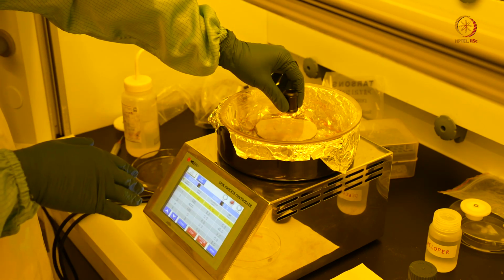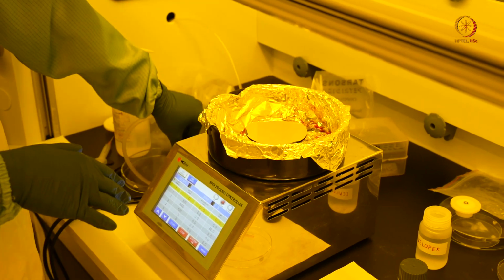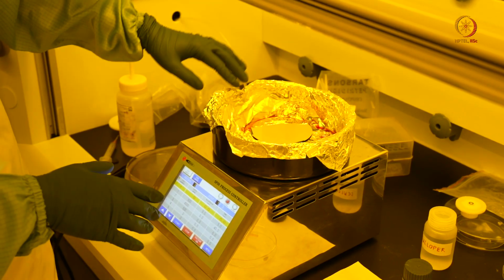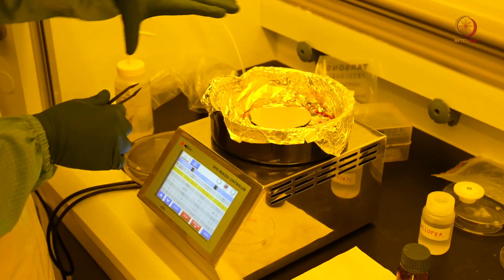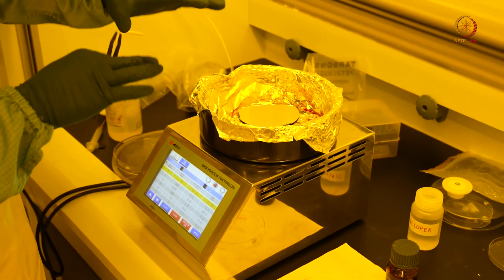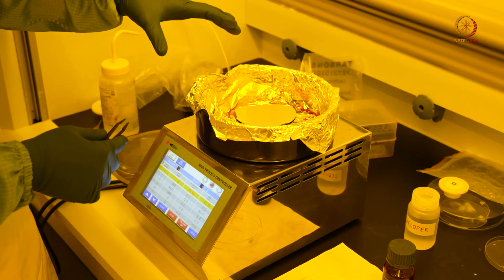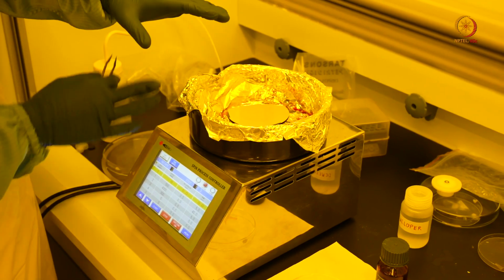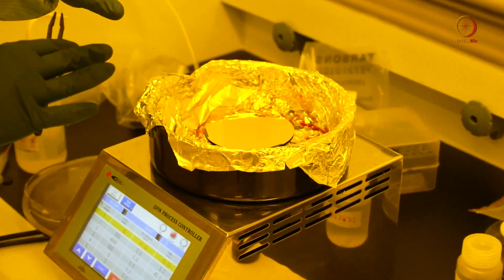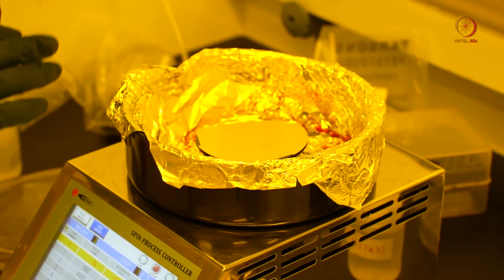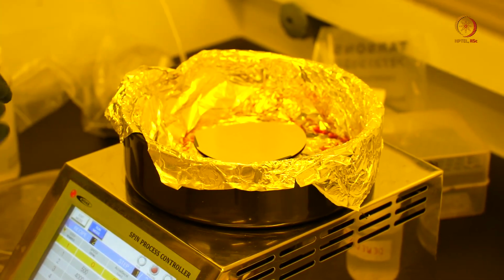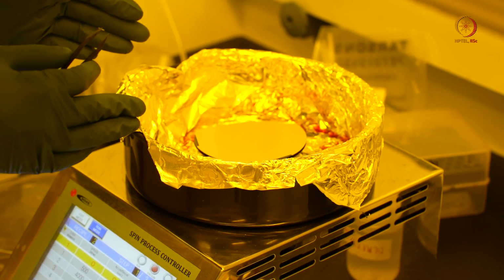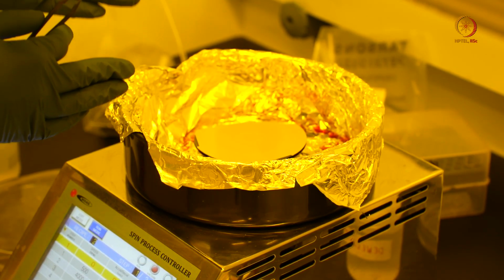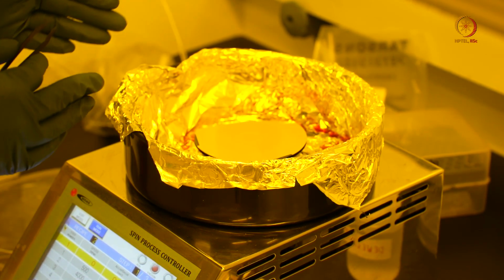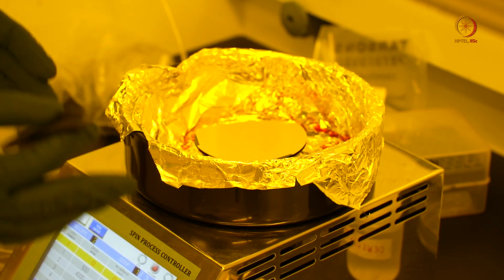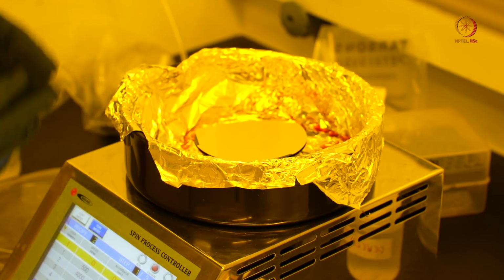So now the spin coating process is done, and you might be able to see a very thin rainbowish tint on the wafer, which previously was pure gold, and now you can see a rainbow kind of shade. That is created by the photoresist that we have spin coated. Now we will take the wafer from here, and we will shift it to pre-exposure bake on the hot plate. We will do that process now.